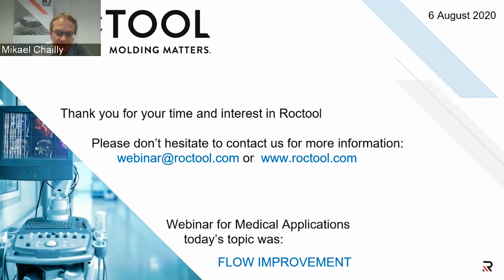We do not have heaters as such within the mold. We have inductors within the mold that generate heat wherever they are located, directly within the steel. So the heat is generated directly into the mold near the inductors and then diffused to the mold surface. For thermocouples, of course, we have thermocouples within the mold that allow us to control the process through temperature, either measuring it to control through time, or controlling directly through temperature.